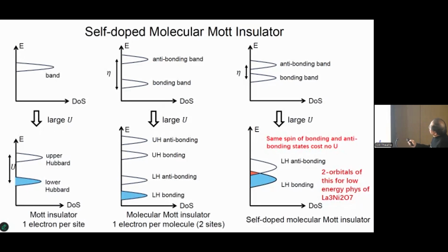And the right side is the self-doped molecular Mott insulator. I still have that, but the spreading of the two bands is not so large. At the large U limit, I have such kind of thing. That means these two lower Hubbard bands will have some overlap. So the red part basically serves as the holes for the blue ones to move. And I shall argue below that the material for the double layer nickelate is actually similar to that, with more complication. These blue ones will actually be two orbitals. And here is a single band orbital.